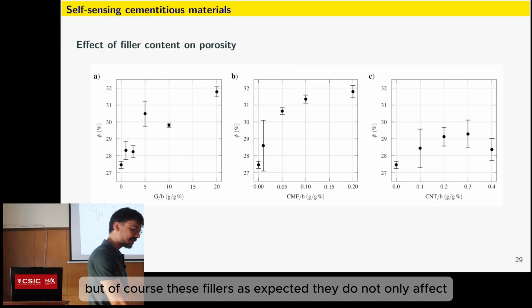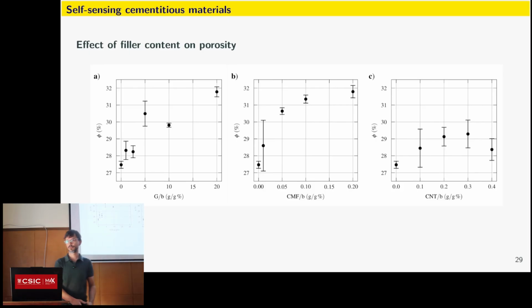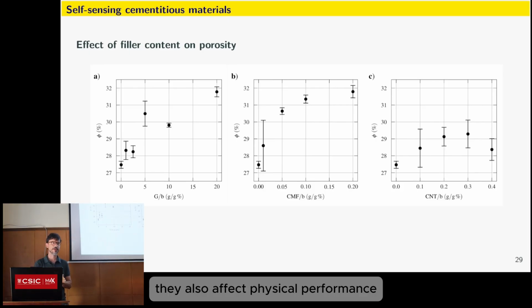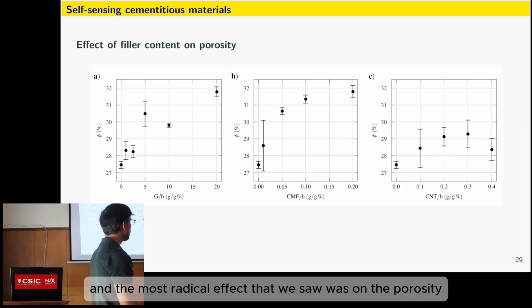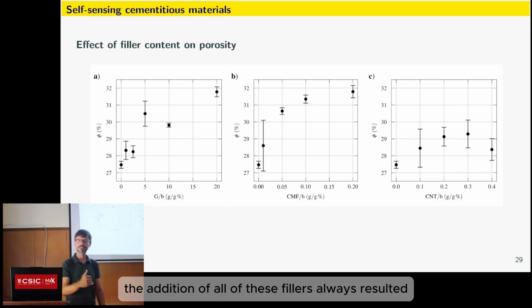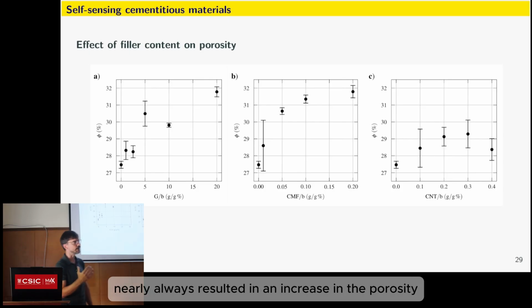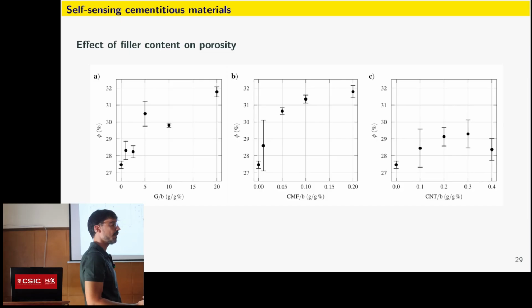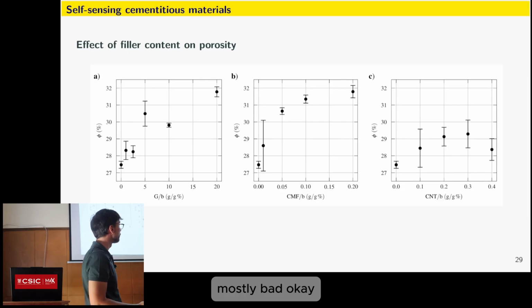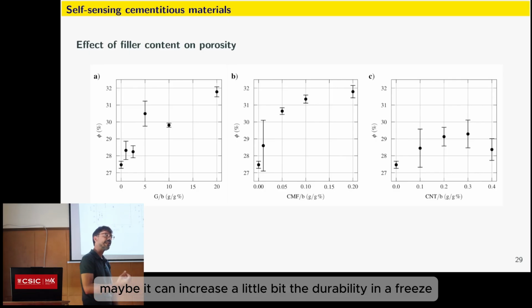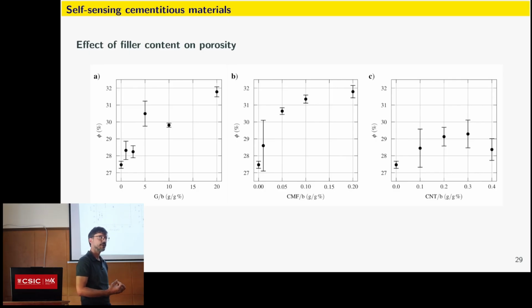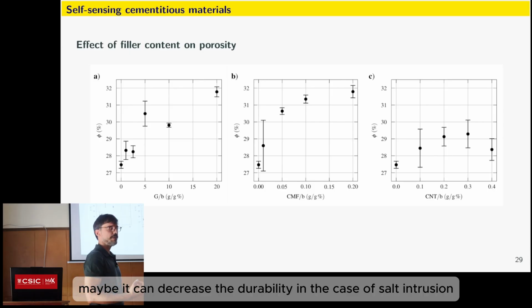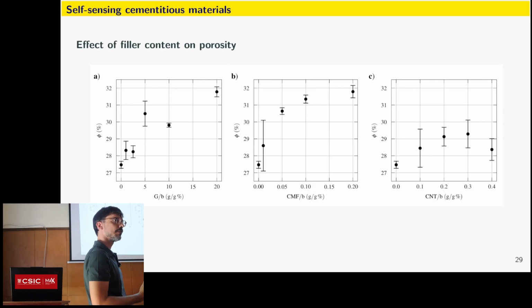But of course, these fillers, as expected, do not only affect piezoresistive performance, they also affect physical performance. And the most radical effect that we saw was on the porosity. The addition of all of these fillers nearly always resulted in an increase in the porosity. Is that bad? Is it good? Well, mostly bad. Maybe it can increase a little bit the durability in freeze-thaw conditions. Maybe it can decrease the durability in the case of salt intrusion. So we need to balance these things out.